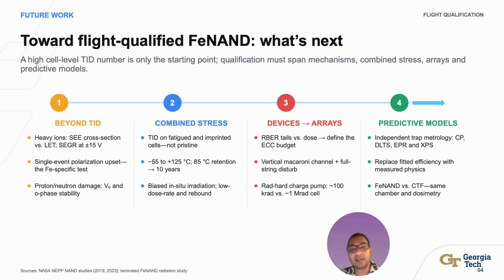So finally, what are the next steps towards a truly flight-qualified ferroelectric NAND technology? We must go beyond gamma total ionizing dose to heavy ion single event upset effects, possible gate rupture at plus or minus 15 volts, ferroelectric-specific polarization upset, and proton and neutron displacement damage. Second, we must combine radiation with cycling, imprint, temperature bias, and long-term retention. Third, we must move from planar devices to vertical strings, arrays, and measure raw bit error tails and